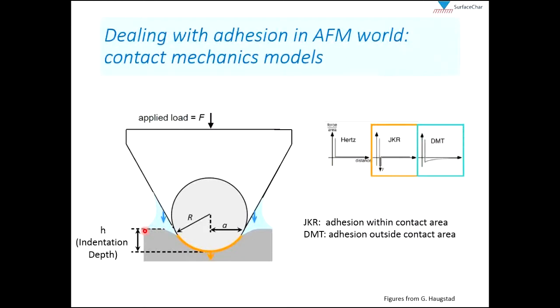Now, I said that in the bulk DMA, they don't have to worry about adhesion. It's macroscopic in the bulk, and that's very fortunate. Now, in the AFM world, which operates on the nanoscale, we do have to worry about adhesion because there is adhesion between tip-sample interaction, especially on a lot of the materials that one might want to probe viscoelastic properties because they do tend to be on the softer and stickier side. So there are two main contact mechanics models available to us to include adhesion in our tip-sample interaction.